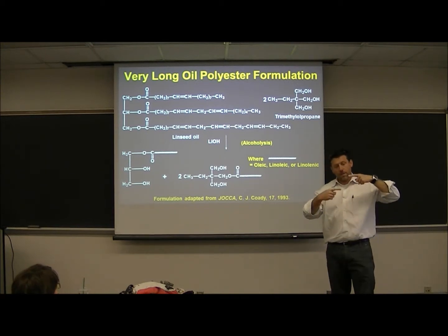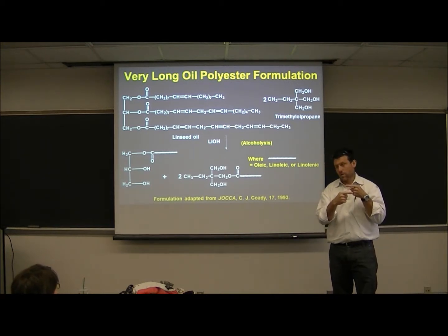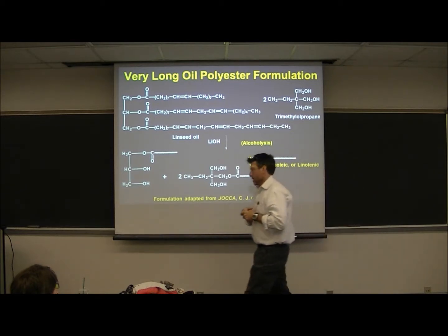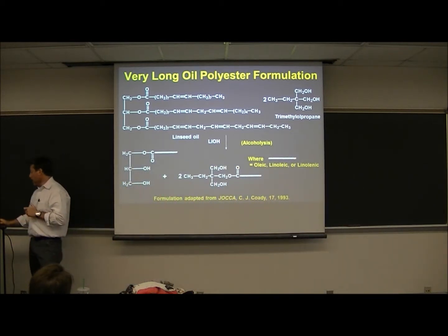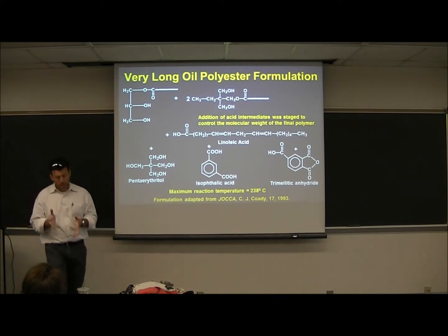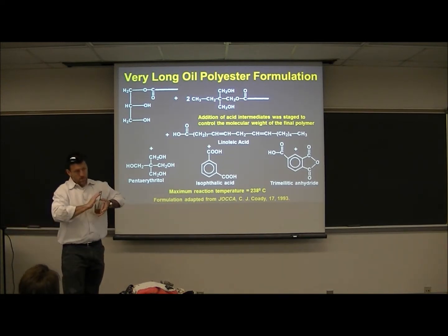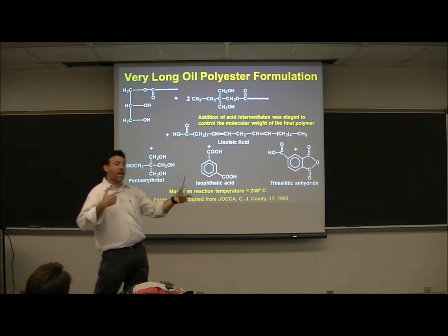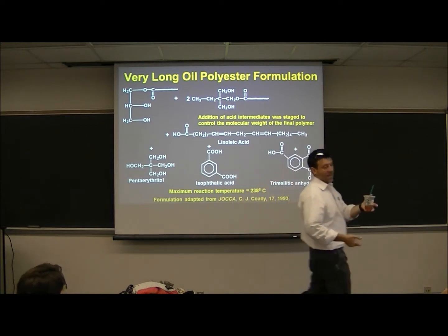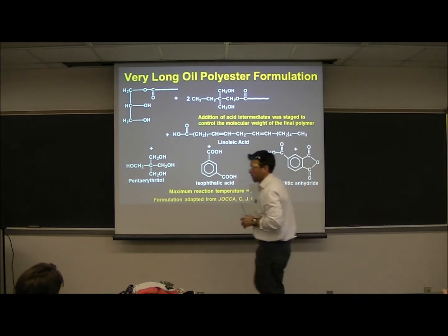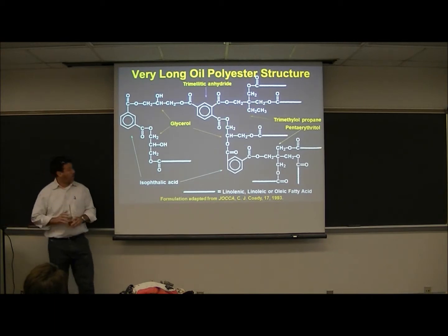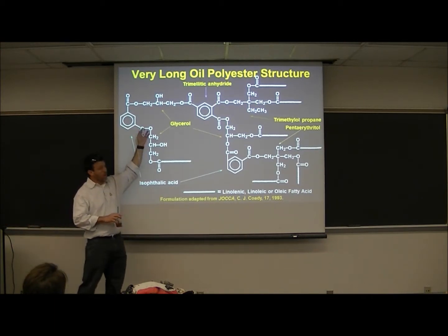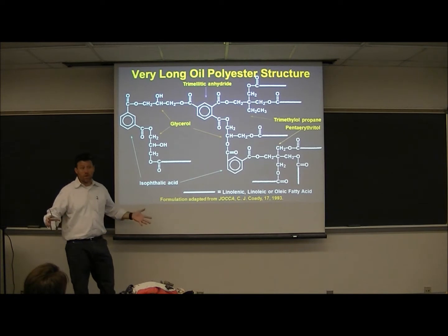But now we have to remember the arrows. The arrows go both ways. So what you don't find on the shelf anywhere really in the world is a polyester of any type that is made in water that sits in water on the shelf. Because what you will measure over time is an increase in acid value. Month over month, the acid value will go up, and as that's happening, we're cleaving these esters. We're hydrolyzing. There's plenty of water there.